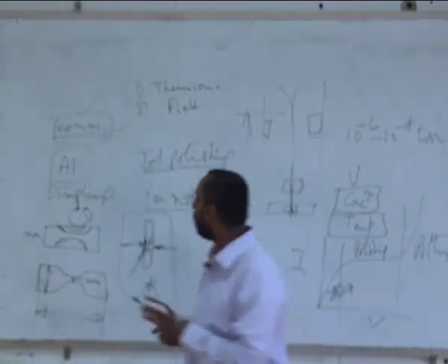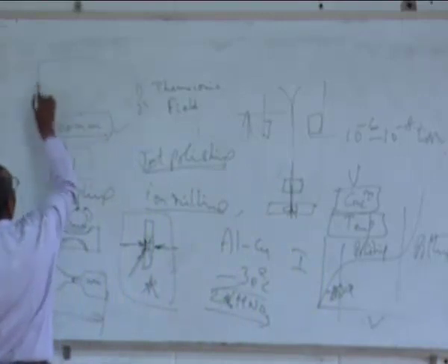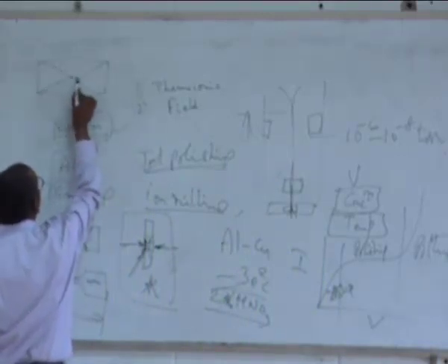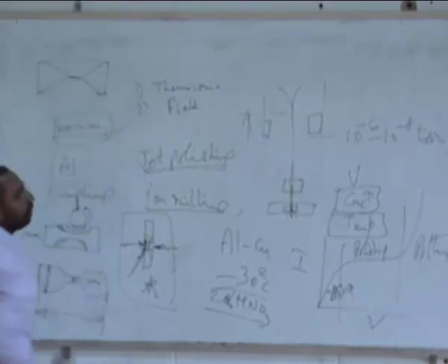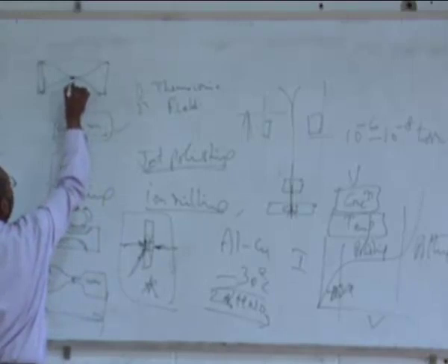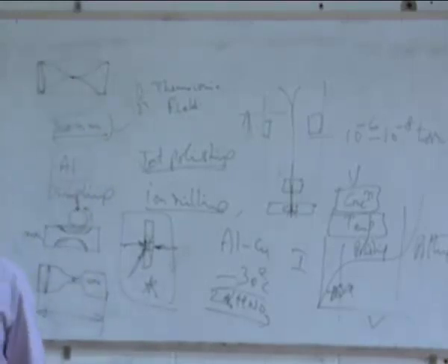So now in that 3 millimeter disc sample, which is a 100 micron sample, you see the center will be the one where the hole is formed. This is 100 microns, but here you will see a thickness of the order of 100 nanometers. And similarly, how do I get such a disc in a ceramic sample? I cannot punch a ceramic sample. Ceramics are brittle. If I punch them, they will break into pieces. So there is a special technique, which we call ultrasonic disc cutting.